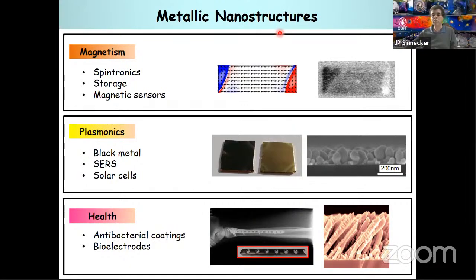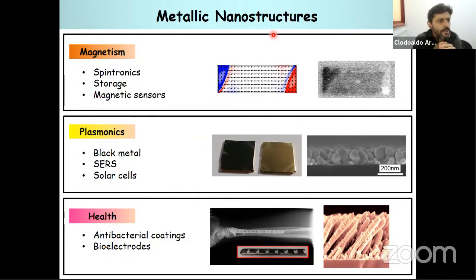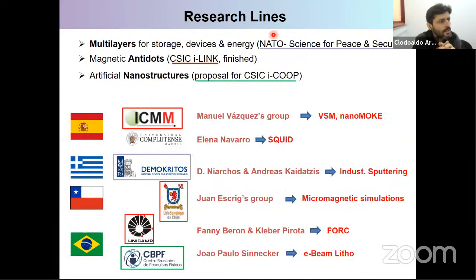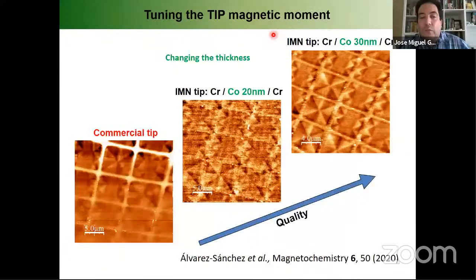I have a last question from Clodoaldo. Please, Clodoaldo. Hi, can you say again why the commercial tip is not good and when you cover it, it is better? Well, when you buy a tip, if you are going to use it to scan a hard disk, for instance, it's quite easy. But when you want to scan a nanostructure, you have to take care of the tip stray field on the one hand, in order not to change the magnetic state of your sample, but also the coercivity of your tip.